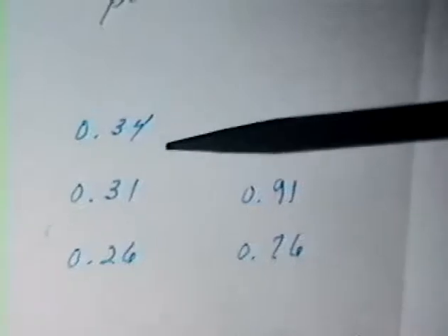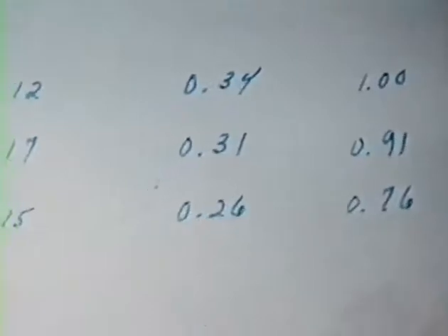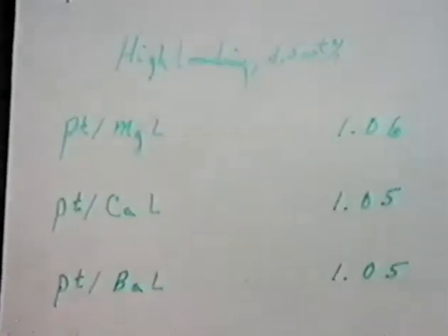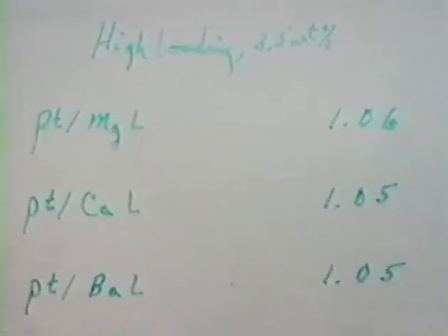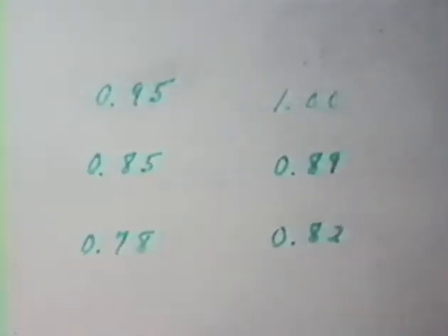It, in fact, exceeds 1 somewhat for these low loadings, and it's about 1. But what's different is the way the CO chemisorption behaves. On some, it's very low. It's about a third of the hydrogen. And in others, it's about equal. Now, I have reason to believe that those catalysts that Amoco and Chevron make that they think are commercially interesting are ones that are more like this. Though in a recent paper submitted from Amoco, they actually quoted our paper and said this was about right. I don't quite understand that.